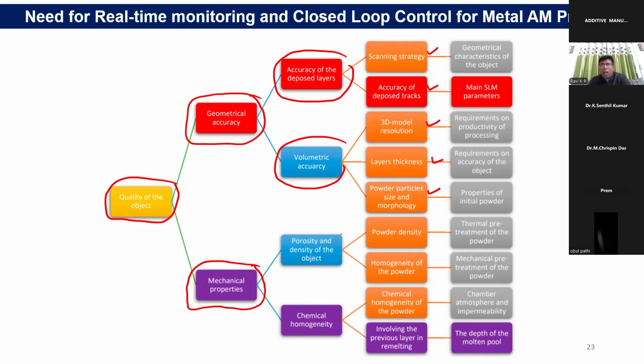But those things are largely affected because when you do this process, we have more than 100 to 150 parameters which can control the entire additive manufacturing process. It is very difficult to control all these parameters. Again, whatever may be optimum parameters for a single layer is not necessarily an optimum parameter for the next layer. So that means we need to make this machine completely smart so that it can identify optimum parameters on its own. That is very important for making parts which have repeatable microstructure and mechanical property without any major defect.